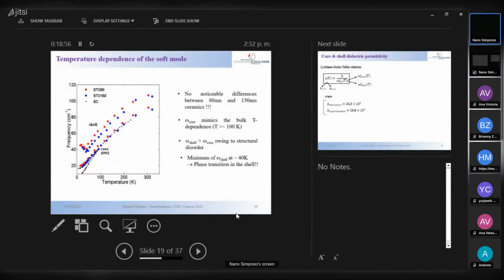And what you see is that for the large grain and for the small grain, the temperature dependences are exactly the same. And so why, if the temperature dependence of the permittivity in both core and shell are the same, why does the effective dielectric response decrease when you reduce the grain size?